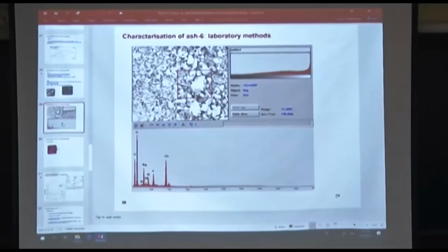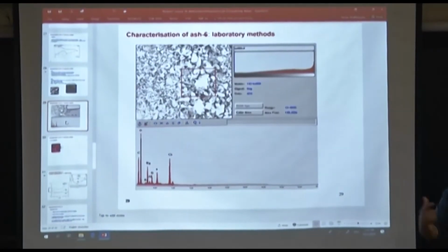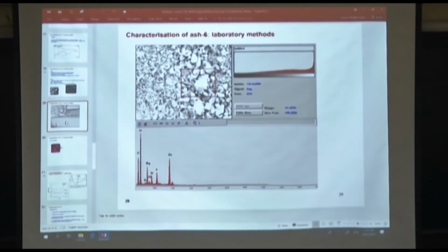But that's the important thing, that is the temperature, exposure to temperature over a longer period of time, that usually makes these sorts of solid materials change from amorphous to crystalline. So X-ray diffraction and EDX are complementary techniques. Sometimes it is good to do the calculations, but it's also good to then verify it through the complementary X-ray diffraction.